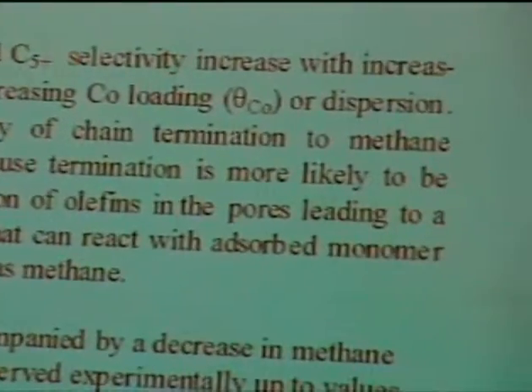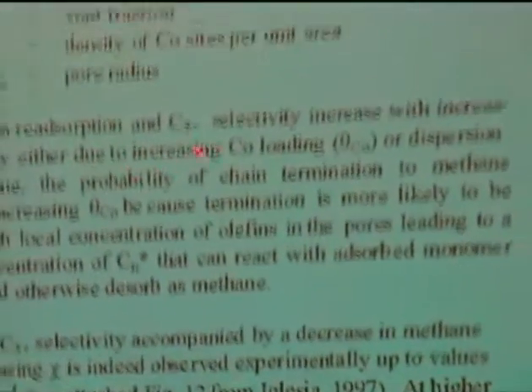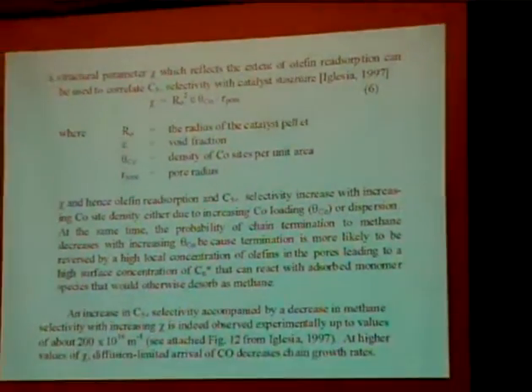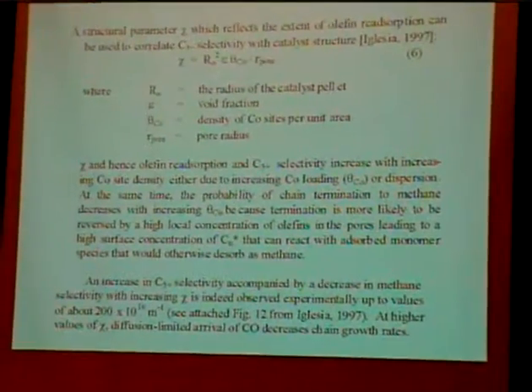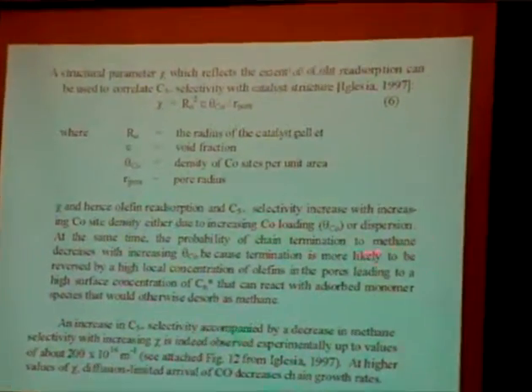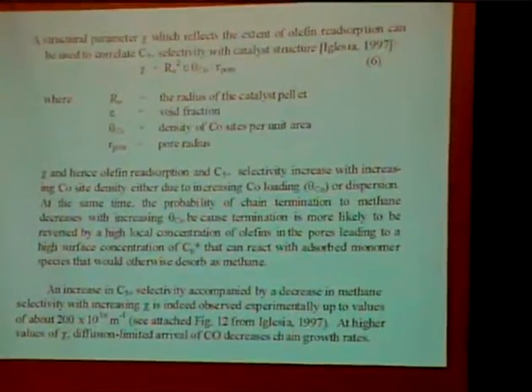What this means is that chi, and hence olefin reabsorption and C5 plus selectivity, increase with increasing cobalt site density, either due to increasing the cobalt metal loading or the dispersion. At the same time, the probability of chain termination to methane decreases, because you're more likely to get olefin reabsorption, and this actually inhibits the termination to methane.